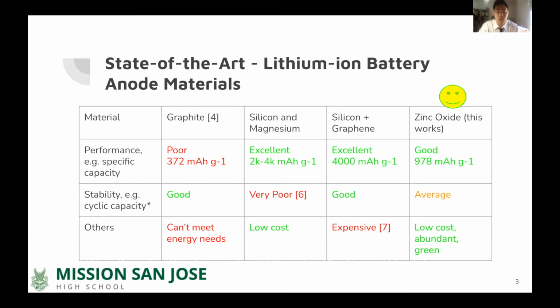Other materials such as silicon and magnesium have specific capacities in the thousands. However, it seems that there's a correlation between specific capacity and volume expansion, which hinders the effectiveness of the material. And thus, a possible solution that has been extensively researched is silicon combined with graphene. This takes advantage of the extremely high theoretical capacity of silicon of over 4,000 milliamp hours per gram, while introducing graphene to trap the silicon and prevent volume expansion. However, this option is still too expensive to begin mass production and be integrated into everyday items.